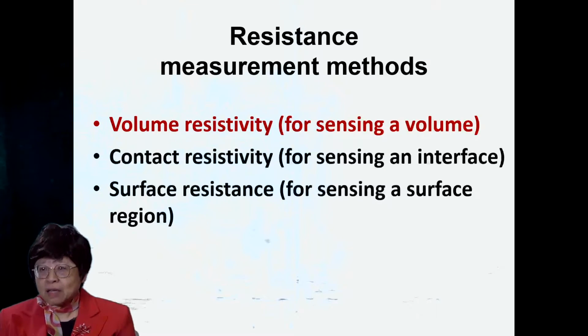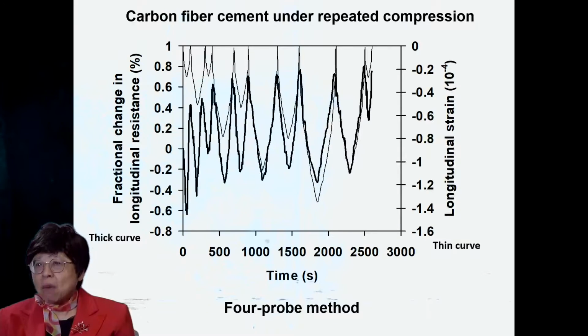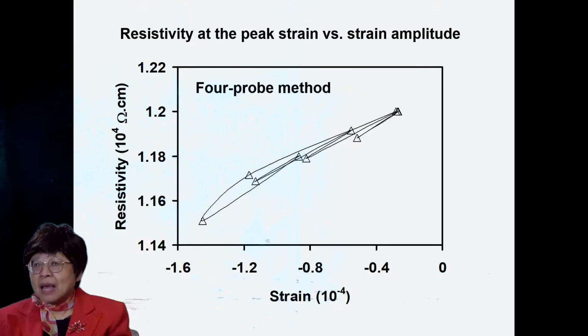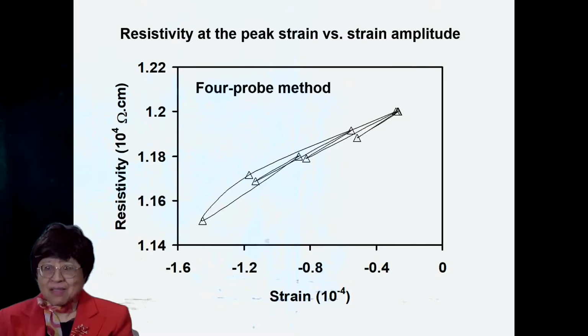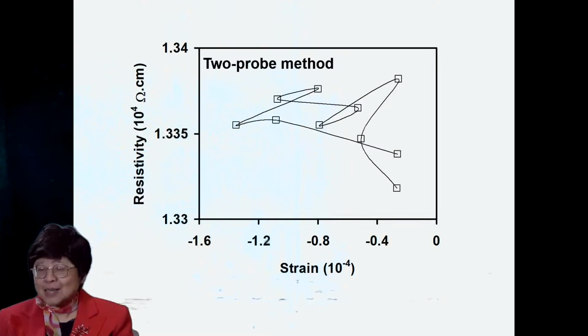And I'll first talk about the volume resistivity. This is carbon fiber cement under repeated compression. Shown in thin line is the longitudinal strain, and I have an arbitrary progression of strains at different amplitudes of the strain, and the bold line is the resistance, and every time one compresses, the resistance goes down. And I can plot the resistivity versus the strain amplitude, connecting the data points in chronological order. And one sees that it's kind of linear and not much hysteresis. And that's done using the 4-probe method. However, if one uses the 2-probe method instead, it's a mess.